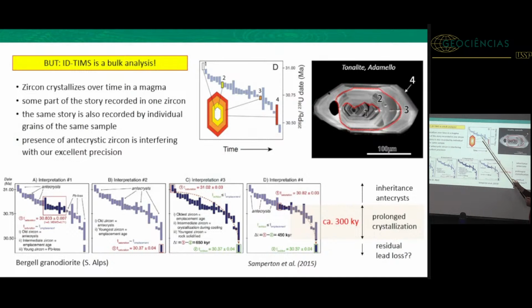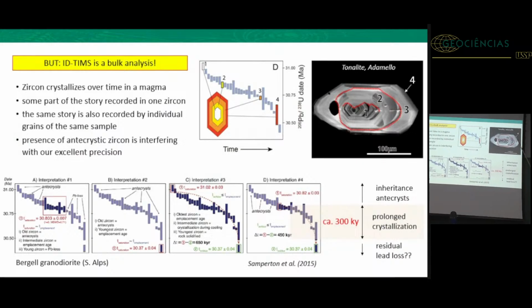So when we look at this distribution of dates here, this is 300,000 years of age difference between the oldest and the youngest grain, and we may see this in a CL image. We see that this center of the grain is not an inherited core. It just crystallized a bit earlier in the same magmatic system, got resorbed, overgrown by zone 2, resorbed again, overgrown by zone 3, and then at the very end you have a thin overgrowth of very high uranium zircon, which is number 4. When we have really good luck, we may find one crystal that only consists of 1, or only of 2, of 3, of 4, etc. But in the normal case we have mixtures.